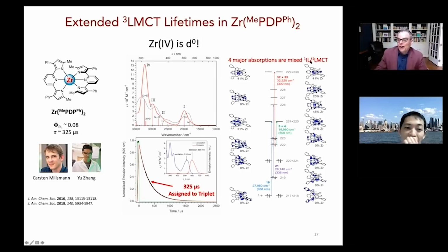But what I would tell you is the reason why the zirconium is so long lived, we think, is because of these intra ligand excited states. Its excited state manifold has a lot of ligand centered character, and that's what's imparting this really long, hundreds of microsecond lifetime. With copper, the singlet and the triplet are both metal to ligand charge transfer in character. In fact, the singlet MLCT is shortening the triplet lifetime. That's ultimately what happens at room temperature. So that's the real difference.